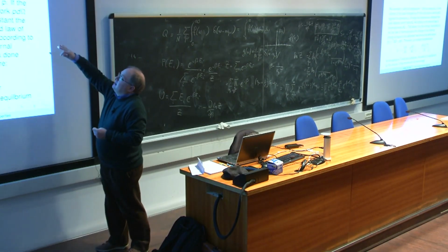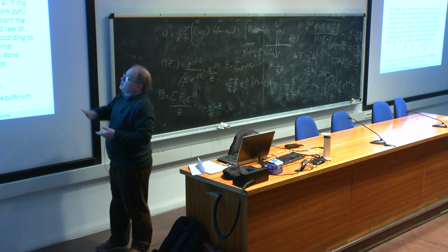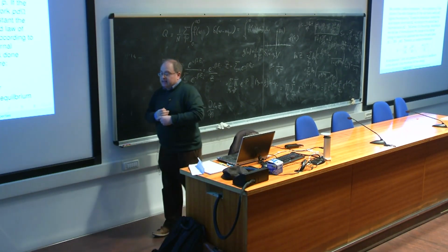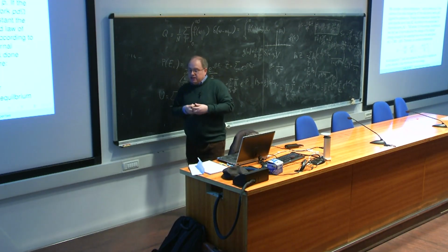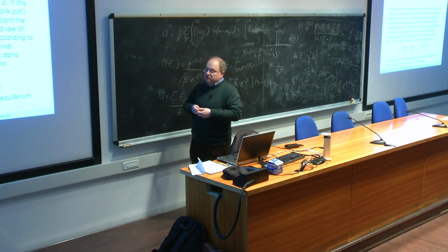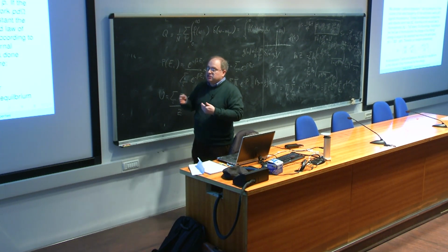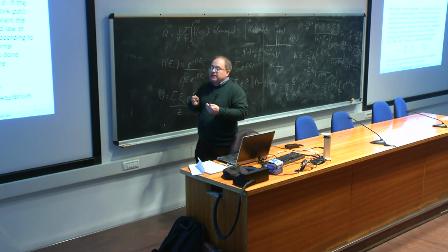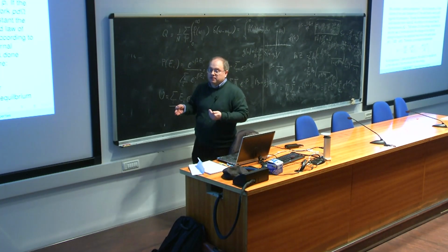It says, consider a solid at temperature T. So what is the purpose? The idea is that if we want to know at a given temperature what is the equilibrium volume, we can calculate the equation of state for our solid. So we calculate the pressure as a function of temperature. And at each temperature, we calculate the pressure as a function of volume and find the volume for which the pressure is 0. That will be the equilibrium volume at that temperature.